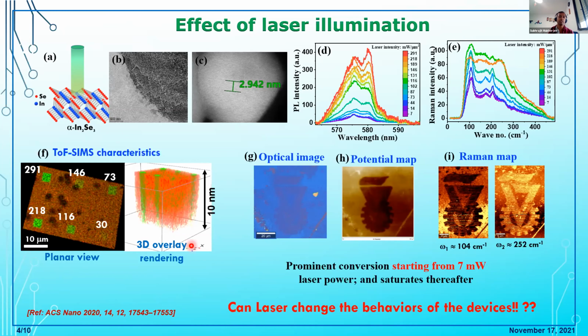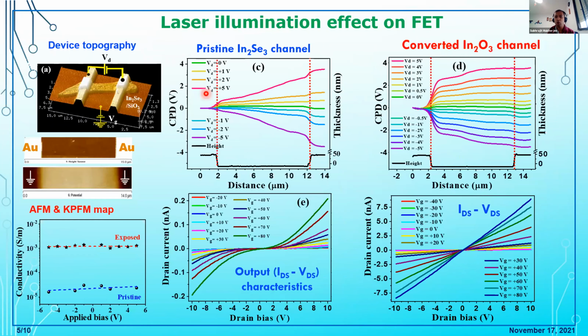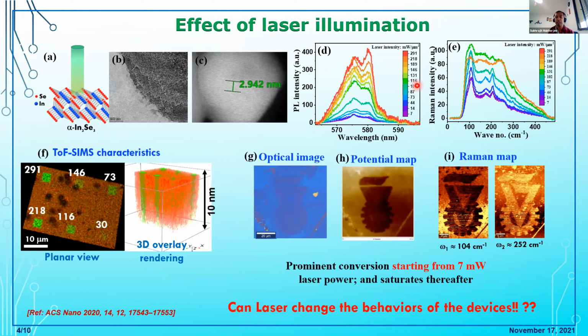So this is the TEM microscopic image. This dark area is actually the laser illuminated area, and the bright area is the pristine indium selenide. And we found these nice nanocrystals formed under the laser irradiation area, which are basically indium oxide. We also checked the PL and Raman of this laser irradiated area, and we see the PL and Raman intensities also change.